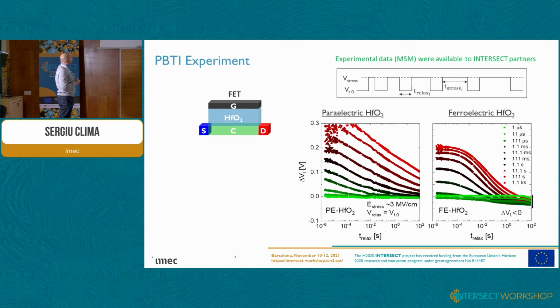But then the longer you wait and measure what happens to the threshold voltage, you see the detrapping. So this is the paraelectric hafnium oxide behavior, and this is the ferroelectric one. So basically, as Johannes just told you, you have to wait for some time for the detrapping to occur in order to see the polarization component there.